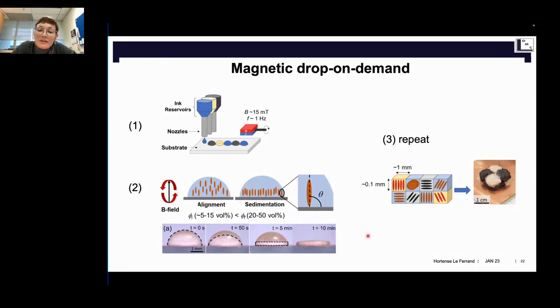And for each voxel, you can change the composition, you can change the orientation as illustrated in this cartoon. Each of these voxels is about 100 micrometers in thickness, and the diameter varies a little bit, more or less around 1 millimeter. And you can create small objects as in this picture.